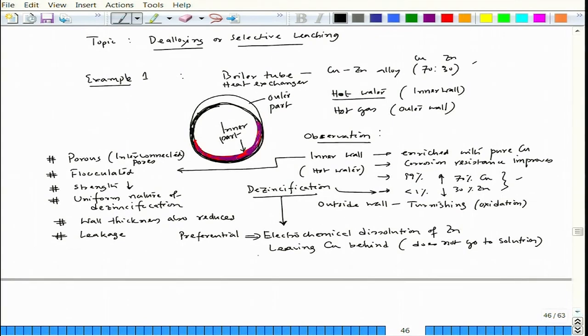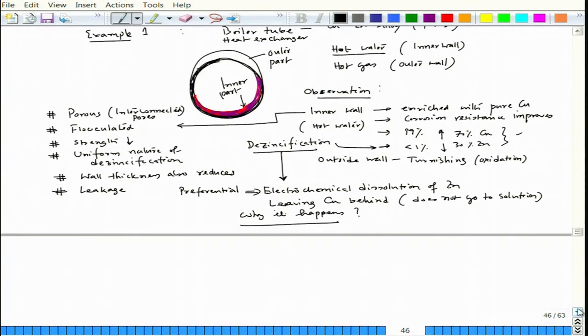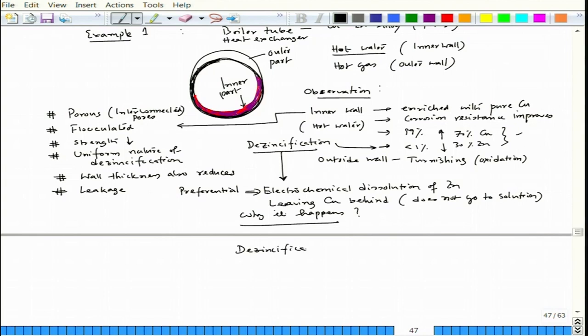The question is why this happens — we need to understand the mechanism. Interestingly, the de-zincification here is happening over the entire wall. But in some cases it might happen locally, and that case we call plug type de-alloying. So there are two variants of de-zincification: one is uniform, and another one is plug type.